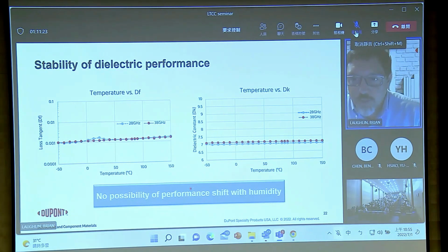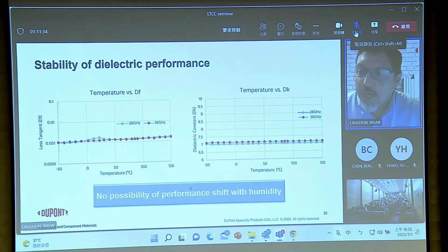And it's a little bit difficult to have a data plot in here, but LTCC is inherently impervious to moisture. It has a dense microstructure, so there's no chance for any shift in material properties with humidity or water absorption, unlike a lot of polymer materials that you could use that are not in kind. And so that makes LTCC not only good at the base design, but in the in-use situation, it's also a very good material.